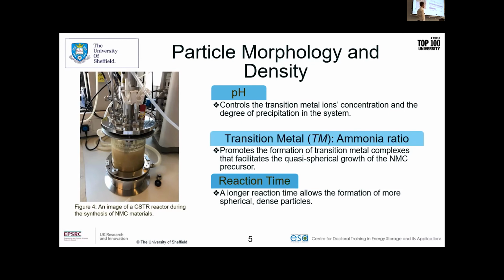The other aspect that we need to look at is the complexing agent. If we've got too much of the complexing agent, it can go the other way and cause clustering of the spherical particles, which then reduces the surface area of the particles and limits the packing ability. And then we've got the reaction time as well, which allows the spherical particles to mature more and densify as Ostwald ripening occurs, and the particles redissolve and reprecipitate to form nice packed spherical particles.